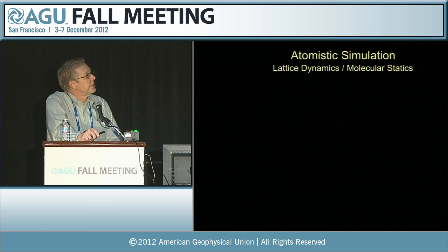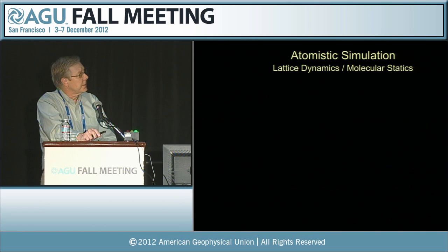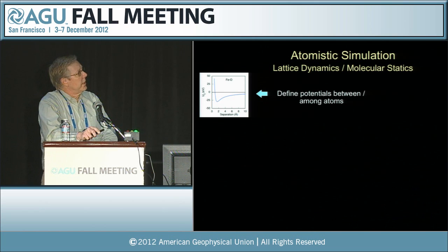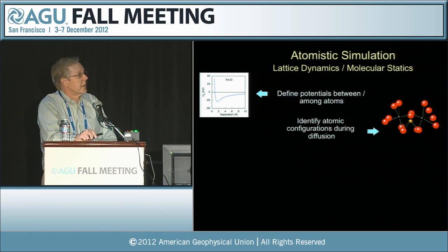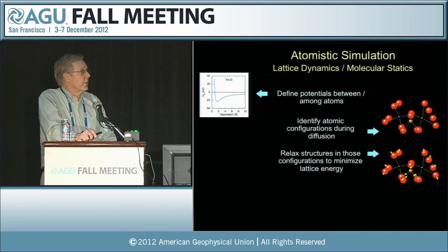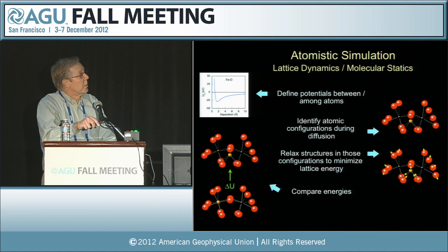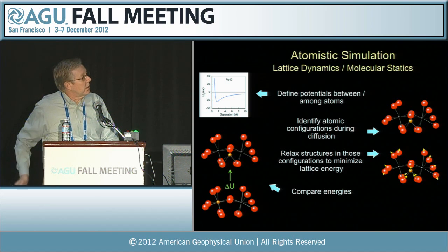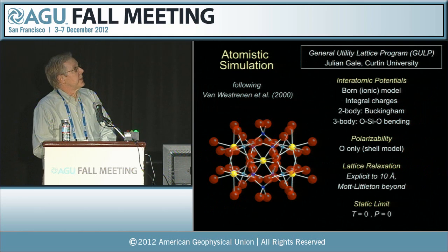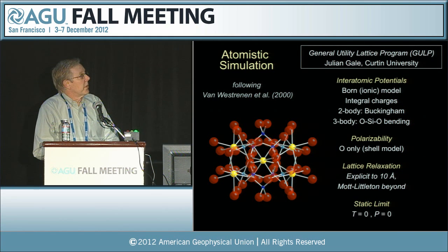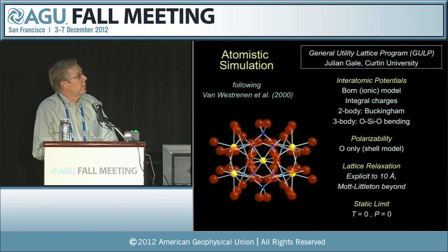So I've tried to approach this using atomistic simulation. These are lattice dynamics or molecular statics calculations. The basic overview here is that we define the potentials that interact between atoms. We identify the configurations that the atoms take during diffusion. We relax those structures to minimize the lattice energy in each of those configurations, and then we compare those minimum energies to see what those energy differences are. Simulations I did use the GULP program written by Julian Gale, and I'd like to thank him for his help.